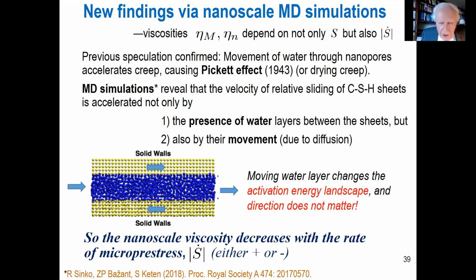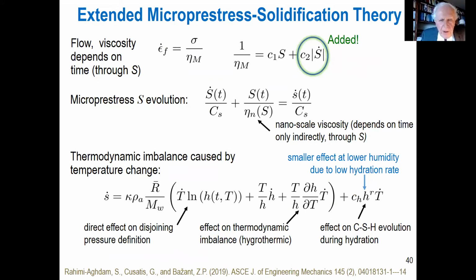So what it means is that the micro-prestress solidification theory has to be corrected by an added term in the equation for S dot. And then we can calibrate for the size effect on drying creep. And the micro-prestress solution then is a similar equation. It translates to thermal effects. That was actually modeled by Cusatis also.